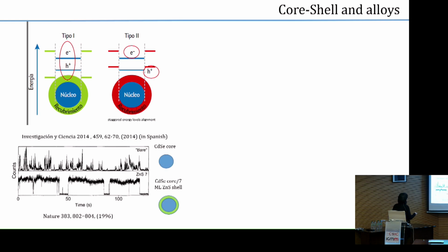So by doing this first type 1 method, by covering the semiconductor with another semiconductor with a higher band gap, it was evidenced already in 1996 that this blinking was very much reduced, but it was not totally reduced. The problem is that sometimes when you have an abrupt interface between the core and the shell, the mismatch between the lattice parameters of the two semiconductors produces more defects. And that's the reason why the crystal is not a perfect emitter.